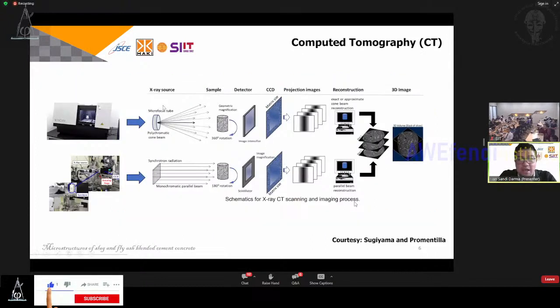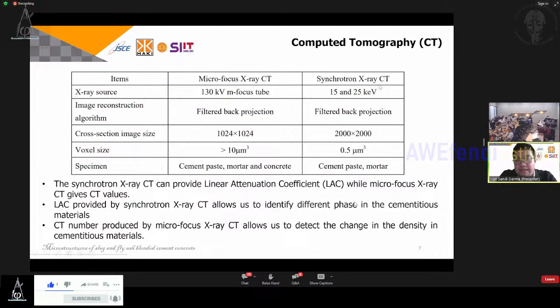In this presentation, I will share two types of X-ray CT. First, microfocus X-ray CT, and second, synchrotron X-ray CT. For microfocus X-ray CT, I used two types: first at Hokkaido University, and the second at Bandung Institute of Technology. For synchrotron X-ray CT, we use a synchrotron in Japan. The difference between them is especially in the focal size. In microfocus X-ray CT, the minimum focal size up to now is maybe around 10 micrometers, but for synchrotron, we could achieve 0.5 micrometers. So very, very small microstructure sizes can be achieved by synchrotron X-ray CT.